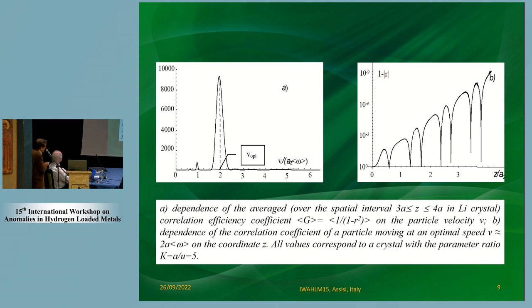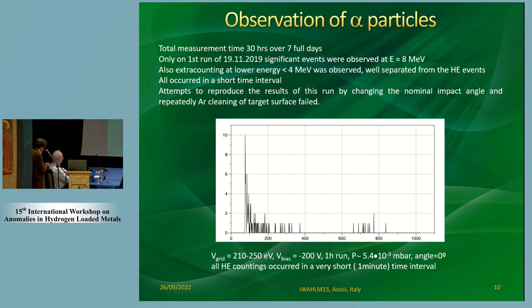And this is an example of 1 minus R, and you see here, after the fourth lattice, this R is very, very close to 1. So this onset of a coherent correlated state occurs very rapidly. They don't need a long penetration into the bulk. So this is what we have measured during this run. Unfortunately, it was only in one case that we had a very, very tiny signal at an energy that can be reconducted to the value 8.3 MeV, which is the alpha particle energy.